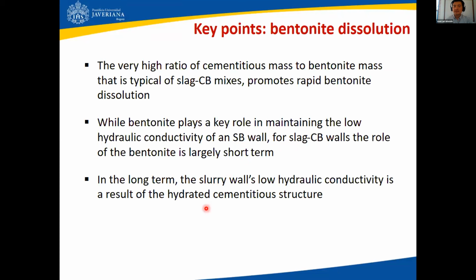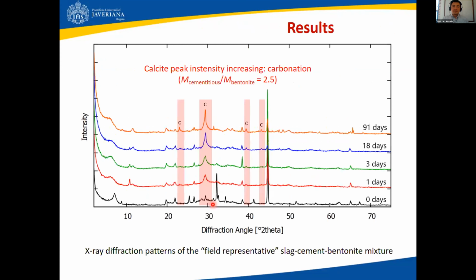And third, in the long run, we believe that the slurry wall's hydraulic conductivity is a result rather of the hydrated cementitious structure. That is the cement hydration products and other products that I'm showing in just a second, not the bentonite, because the bentonite disappears rapidly with time.